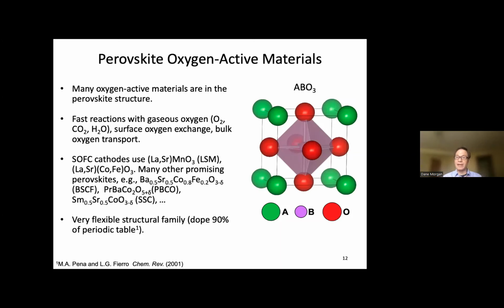And one of the most widely used materials for this, and the ones we're going to focus on, are perovskites. You've probably run into perovskites if you do material science. They are kind of everywhere. This is their structure. They have two cations, an A cation on the corners of a cube, a B cation in the center, and then surrounding the B cation is an octahedral environment of oxygen. And a lot of them are very good at reacting with oxygen and CO2 and H2O. They have good ability to exchange oxygen in their surface, and they have good ability to transport oxygen through their bulk. So they are active oxygen materials.